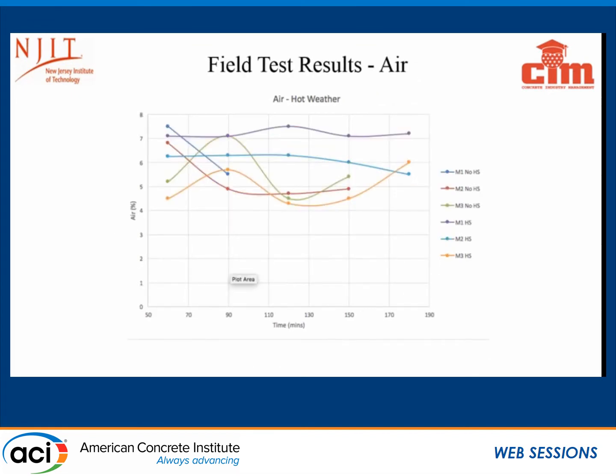Air, of course, is a major concern because as the mix is extended, you can have a loss in air. At each interval, when we tested the mix in 30 minutes, we would check the slump and air. In some instances, which we'll see in the results later on, we had to retemper with both the high-range water reducer and the air entrainment. But generally, all things considered, the air was fairly consistent when you use hydration stabilizer.